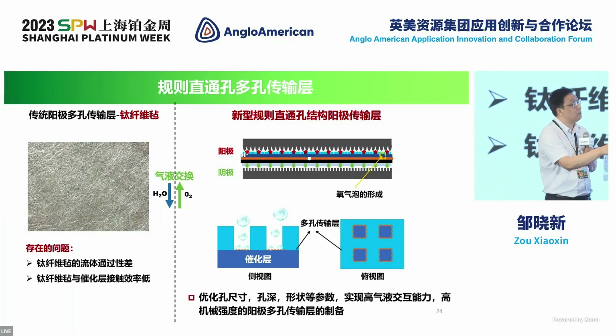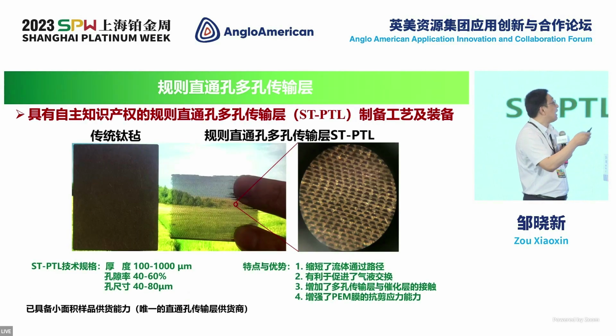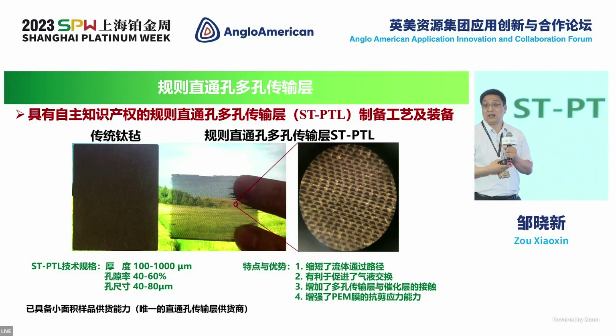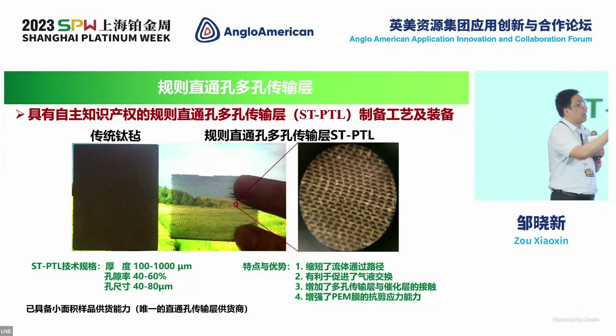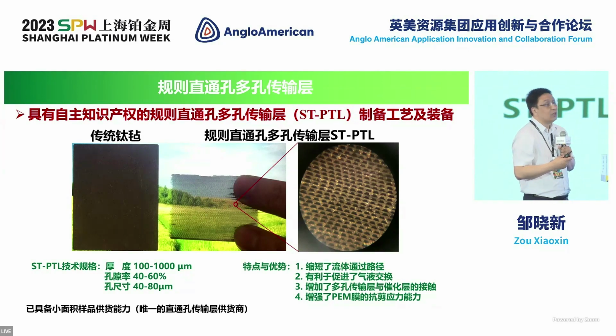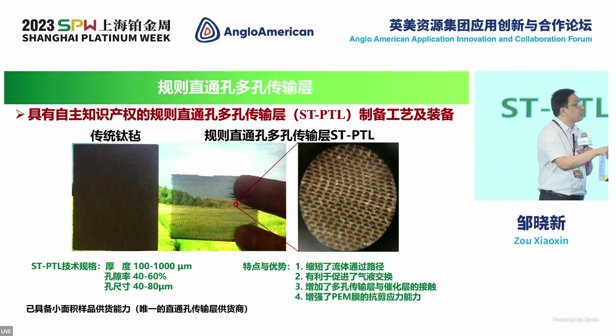One is the transmission rate of fluid is pretty low, and the second is the contact rate with the catalyst layer is pretty low. So what we do is we have developed this very new type, straight pore structure. So you can see from the left-hand side, this is a photo of the traditional titanium cloth, but with our technology, if you put it under light, you can see that the light can come through and the fluid can also come through. There are many advantages in our technology.